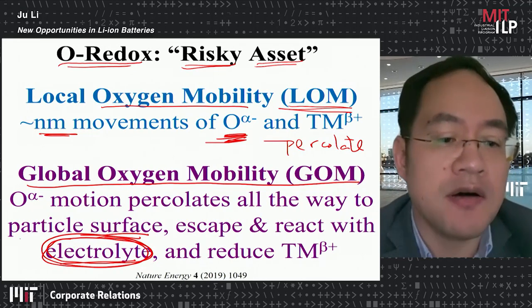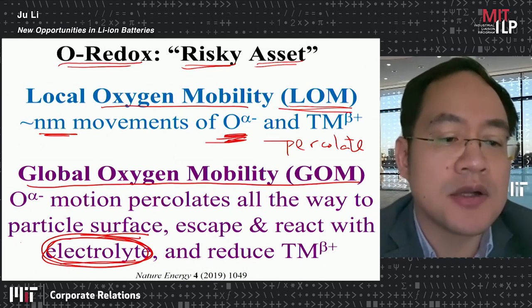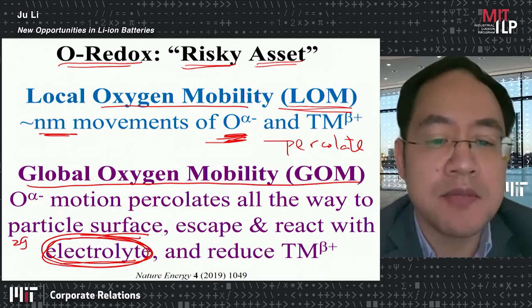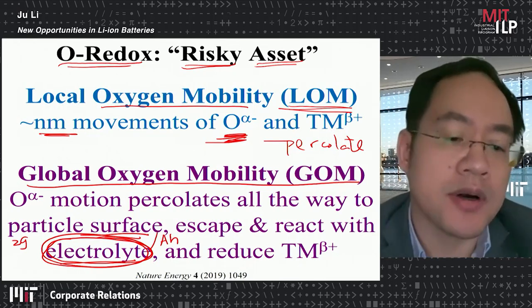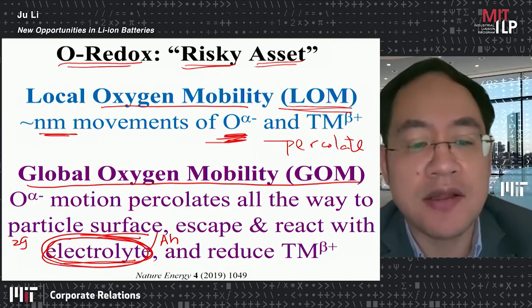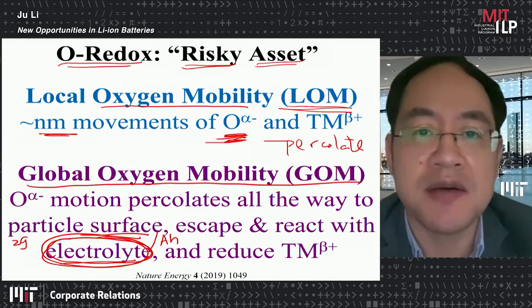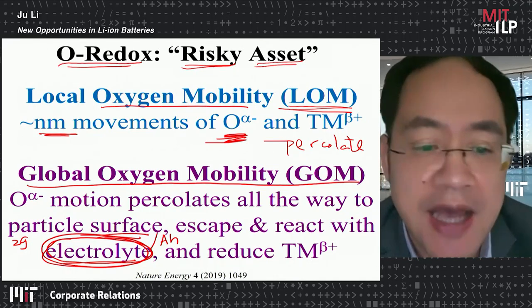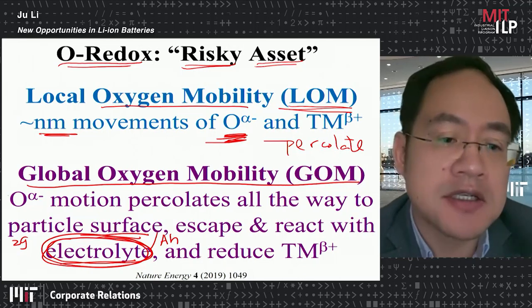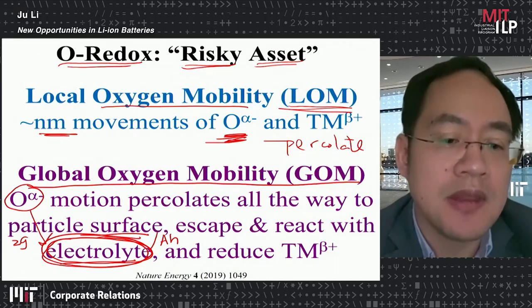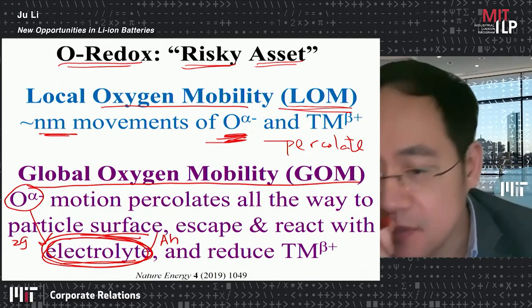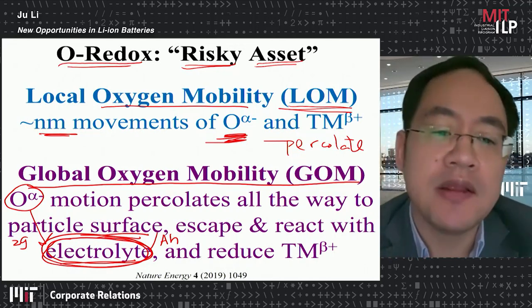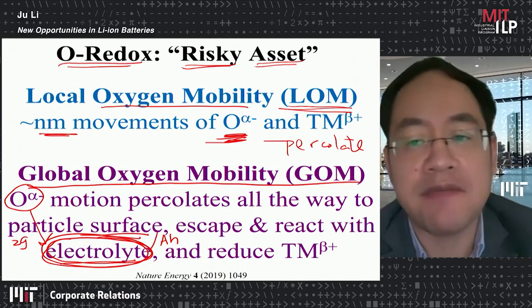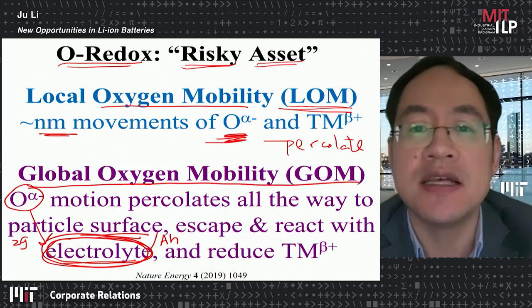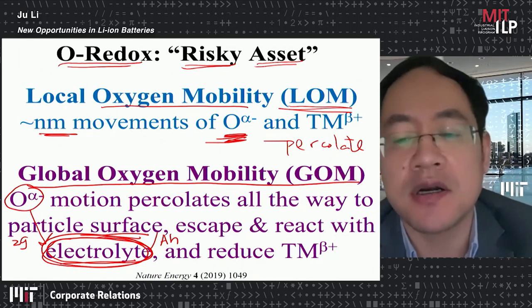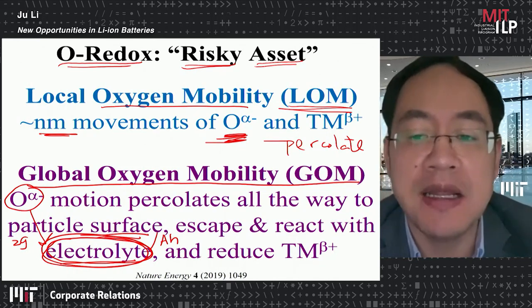In industry, very often you use something like 2 grams of electrolyte per ampere hour, and you're going to show that this electrolyte weight is actually only 40% of your cathode weight. So if this oxygen reacts with electrolyte, it's very bad. And also, if it escapes, you're going to have oxygen vacancy, and this oxygen vacancy actually drives further reconfiguration, further